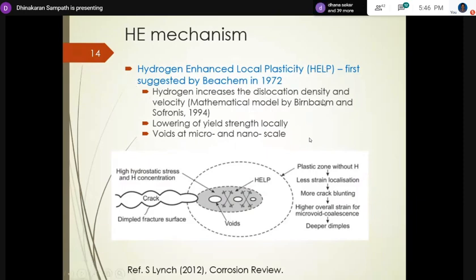Once several of these happen, that is when we see yielding and further hardening, depending on the material type. So if dislocation density and velocity increase, then more plasticity is promoted in the presence of hydrogen, leading to lowering of yield strength locally. This is like void formation, as we saw in the case of in air, but the size is very small because the hydrogen actually localizes.